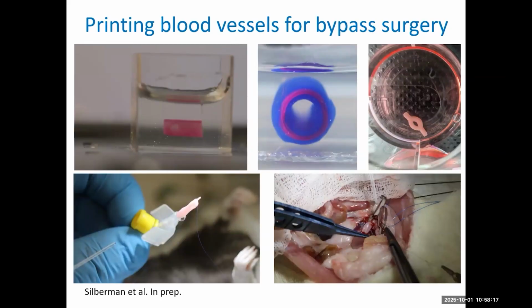But when we talk about the small scale capillaries, as I mentioned, we currently cannot control the printing of these capillaries because there are limitations for the printers. The printers can only print about 100 micrometer blood vessels in diameter. And what we've decided to do is to use 4D printing to print the blood vessels at 100 micrometer in diameter, and then to trigger them to shrink and collapse and to form these small scale capillaries.